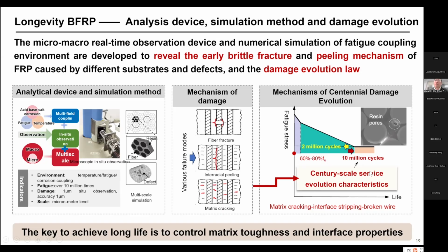So if failure is different to that of the steel, we need to propose a kind of new method to give a different index for this composite material, like the 10 million cycles instead of 2 million cycles for steel fibers. So by these ways, we can make the failure modes of composite materials under the testing fatigue consistent with the real fatigue loading.